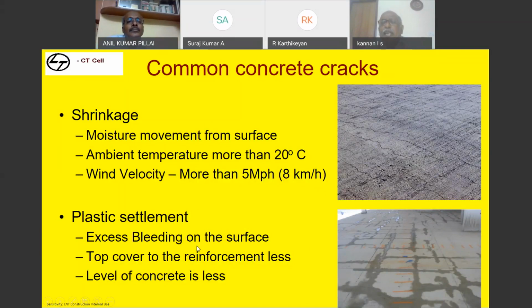This is the pattern of shrinkage crack. The pattern is normally haphazard cracks, haphazard parallel cracks, or even interconnected cracks, but it is all haphazard in nature. Shrinkage cracks normally happen due to moisture movement from the surface. That is the reason we are telling you, please cure the surface and keep it moist. When the concrete loses water from the surface, drying and wetting can happen on the surface, which will lead to cracking; the surface will shrink and crack.